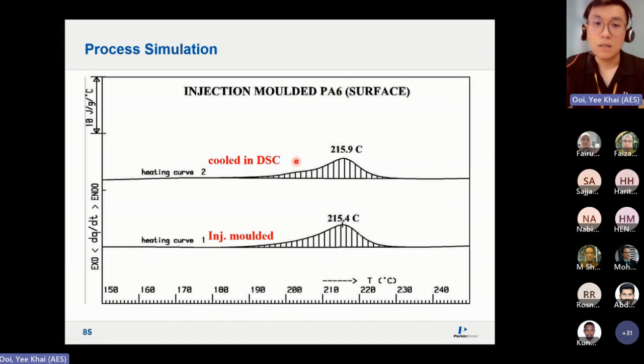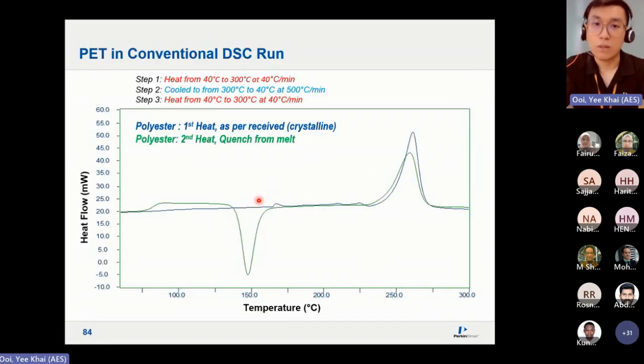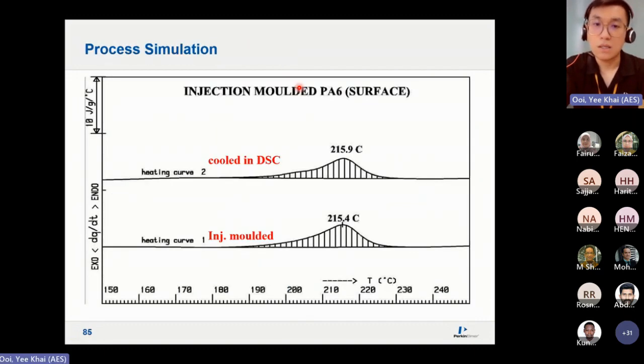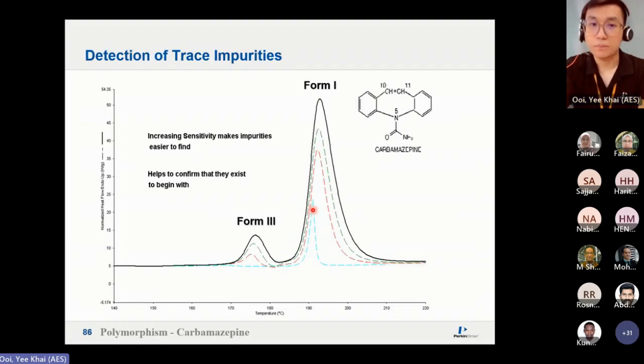So what we do is we melt it, and then we cool it down very fast, like what we did just now, at a very, very fast rate. And then the end product, we reheat it again. So now the melting point is actually comparable to how we did it in injection molding. So we can use DSC to simulate the processes as well, and even detect trace impurities.